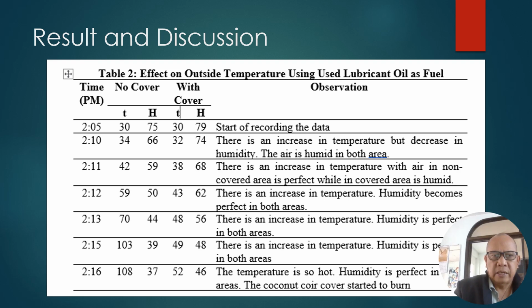In gathering the data, I presented table 2 showing the effect on outside temperature using used lubricant oil as fuel. I started my observation at 2:05 p.m. And it shows that the temperature is 30 degrees Celsius. Then the humidity is 75. That is for the no cover part of the furnace, while with those with cover, it is 30 degrees Celsius in temperature, while the humidity is 79.